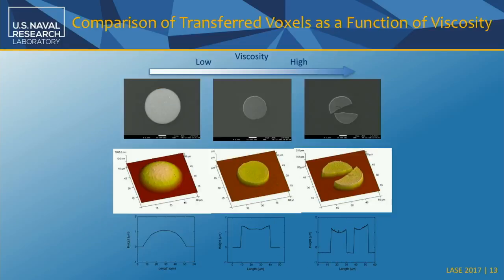So here, if we look at AFM and SEMs of, again, these silver nano suspensions of varying viscosity. So this is of the order of about 10 centipoise. This is of the order of a few 100,000 centipoise, and this is over 1 million centipoise. And you can see that we have a drop here, so that's why we end with a hemispherical shape.